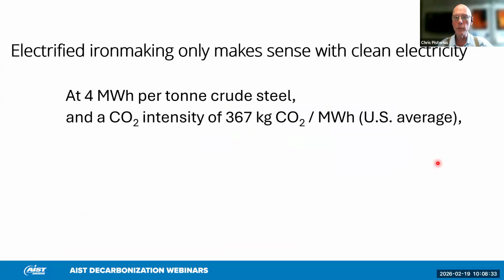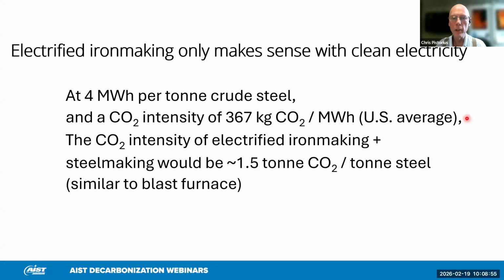And just to emphasize that we need clean electricity for this to make any sense at all. It needs to be essentially zero carbon electricity. Because if we take the US average CO2 intensity, of course, it varies with season, but around 360, 370 kilograms of CO2 per megawatt hour. If you multiply those two numbers, then we are back at 1.5 tons of CO2 per ton of steel. If we just connected one of these plants to normal grid electricity, we would be back at a blast furnace. So we really do need large amounts of very low carbon electricity at low cost. So that will undoubtedly be a challenge.